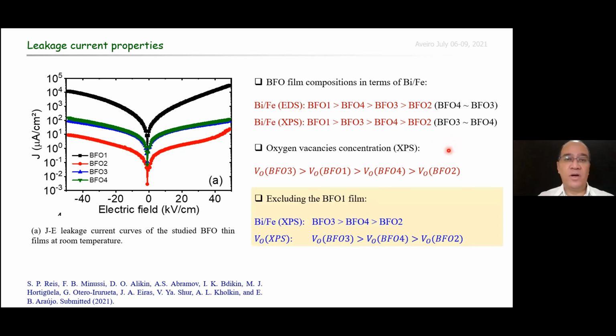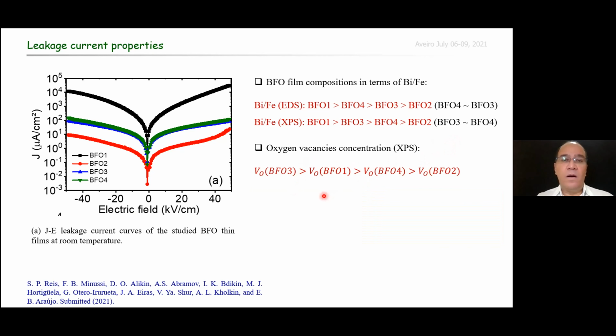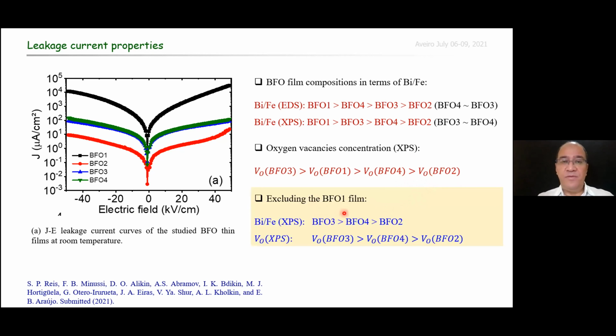On the other hand, from XPS analysis, as summarized in this line, the oxygen vacancy concentration was higher for BFO3 and smaller for the BFO2 film, and intermediate values for BFO1 and BFO4. Remember the composition of these films shown in the table in the previous slide. Okay, excluding the BFO1 film, we observed that oxygen vacancy concentration is directly proportional to the bismuth amount in our films.